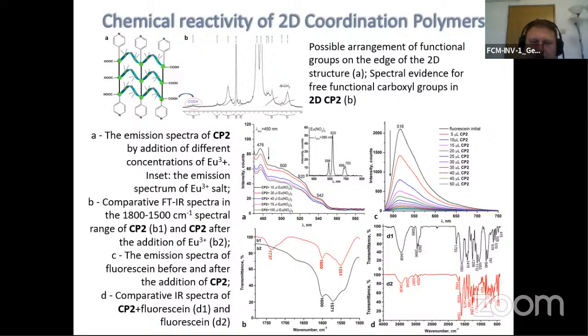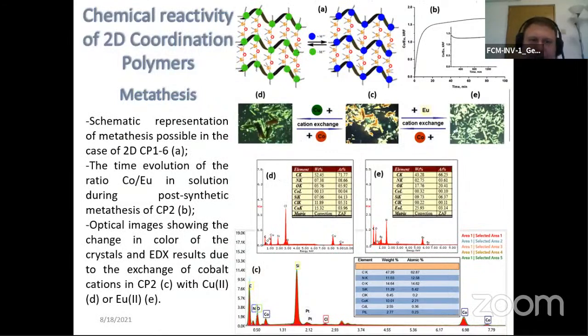The functional groups that are on the edges of the two-dimensional network show chemical reactivity. There is a possible arrangement of free functional carboxyl groups at the edge of the two-dimensional layer. And we can see the analysis by fluorescence spectroscopy and infrared spectroscopy demonstrate the complexation of free carboxylate groups of different metal ions, such as ions of europium. And these polymers showed the metathesis reaction, where they can exchange cations, such as exchanging cobalt with copper or cobalt with europium ions with a respective change in color.